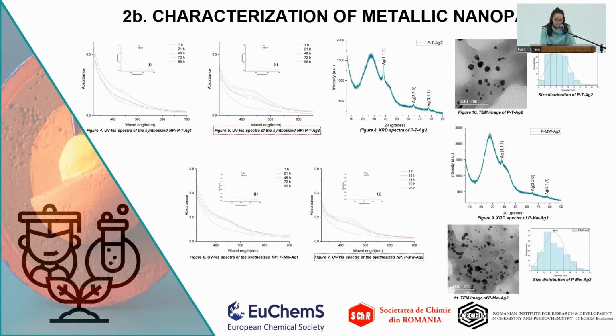From the XRD technique, the XRD technique was used to confirm the formation of the nanoparticles, and the samples display the diffraction peaks which correspond to 3 diffraction planes, which are indicated. And the phase can be identified as silver in a cubic crystalline system.